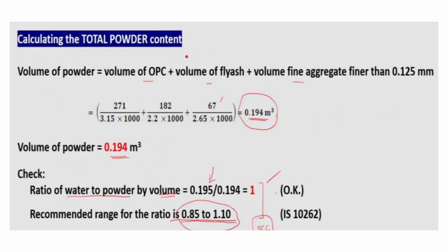Now calculating the total powder content. The volume of powder is basically the volume of OPC plus fly ash plus fine aggregate finer than 0.125 mm, as we know. So that comprises the powder content. Calculating the volume, we get the volume as 0.194 meter cube. So volume of powder is 0.194 meter cube, and then the ratio of water to powder by volume.